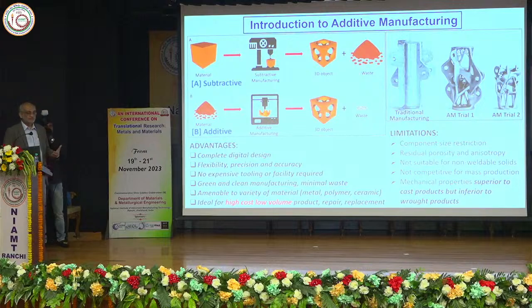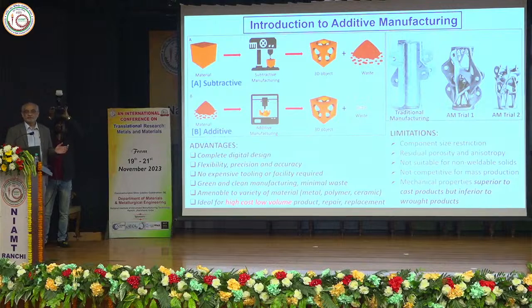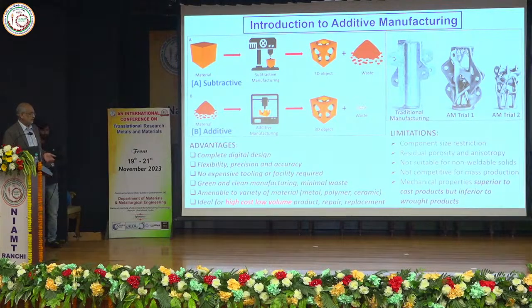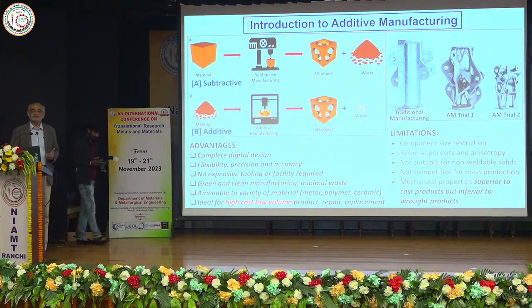That's one of the major concerns. The other concern is the heterogeneity in terms of composition and microstructure, but that can be well managed within a very short length scale. So when you have segregation or variation of density over 1 millimeter, you can easily make it out. But when that length scale shrinks to 1 micrometer or less, it doesn't quite affect the overall integrity of the component. Property-wise, one may claim this is certainly going to be better than normal cast products, but cannot compete exactly with wrought products. So somewhere in between.